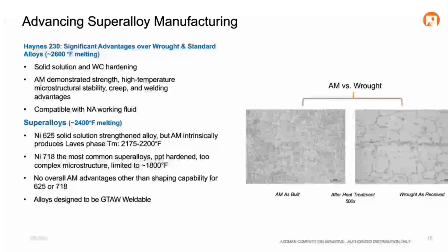Really, where these alloys have seen a lot of use is because they were well suited to having solidification temperature ranges that make them suitable for gas tungsten arc welding. They didn't really have the weldability challenges of some higher strength alloys, such as MARM 247 or some of the Waspaloy alloys, where you run into weldability issues and reheat cracking issues from gamma prime formation, things like that.